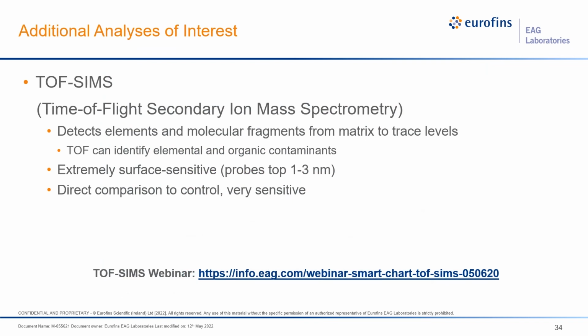So TOF-SIMS we didn't do in this case because we saw stuff right away. TOF-SIMS, the time of flight secondary ion mass spectrometry, looks at elements and molecular fragments from the matrix, and it's also very surface sensitive. It's 1 to 3 nanometers. And what we would do is directly compare our results to a control in order to see if, say, amines are present. Now, in the case where you see some sort of gross contamination like we did on some of these, the TOF-SIMS may not be necessary.